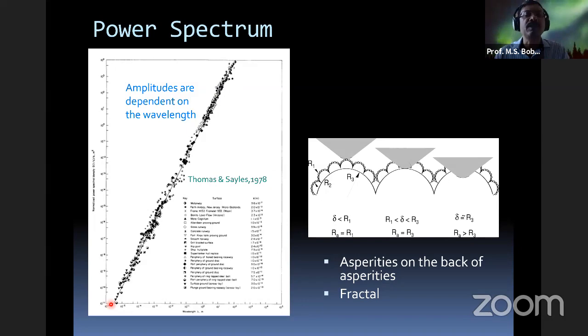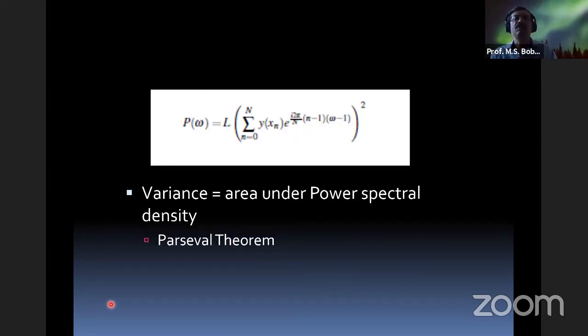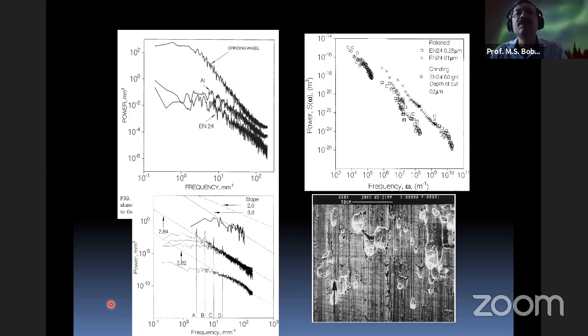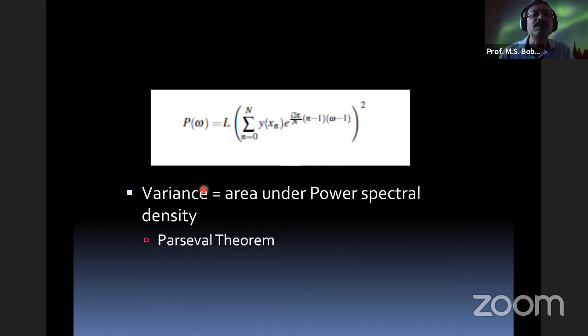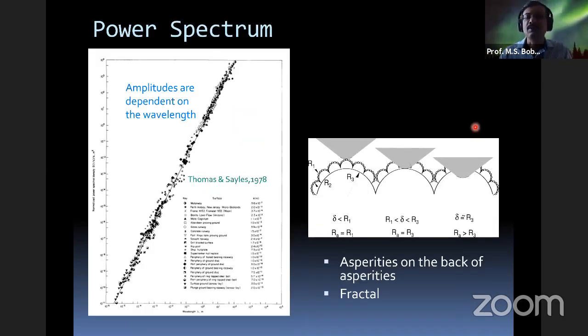And how do you get that power spectra? You don't have to worry about this. So this shows the power spectra of various surfaces. This is the roughness of a grinding wheel. This is the roughness of a surface produced by this grinding wheel on EN24, that is a steel surface. And the middle one is the same grinding wheel, same depth of cut, but the roughness produced on an aluminum surface. Here it is frequency; in the previous curve, it was wavelength. Wavelength is nothing but 1 by frequency. That is why the curve looks reversed, but otherwise it is the same thing.